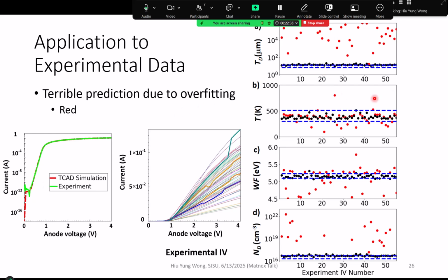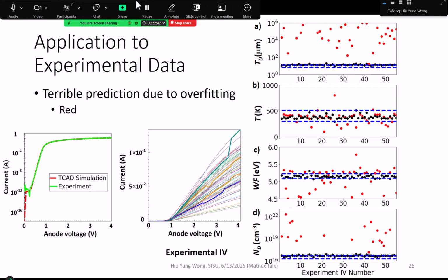So now we ask it to predict. Now, as you can see here, we try to predict the 4 parameters. We put this as the expected range. For example, the thickness should be between these two blue lines, or the temperature being measured is between 300 Kelvin and 500 Kelvin. The work function should be this. And then we also put the black dot, I'll talk about this later. And then we use the machine to predict it.